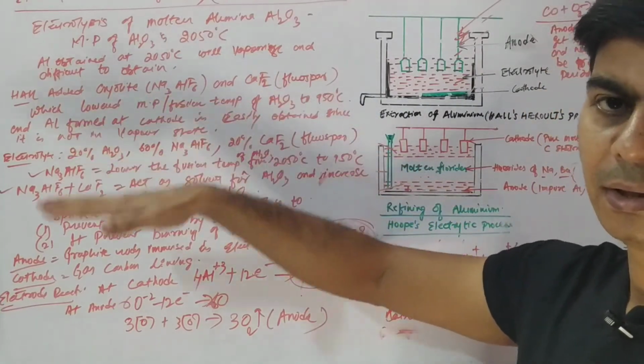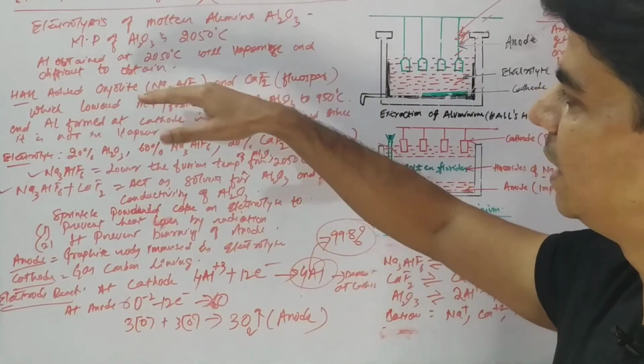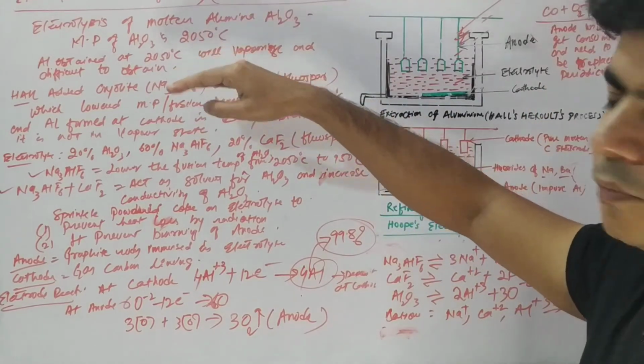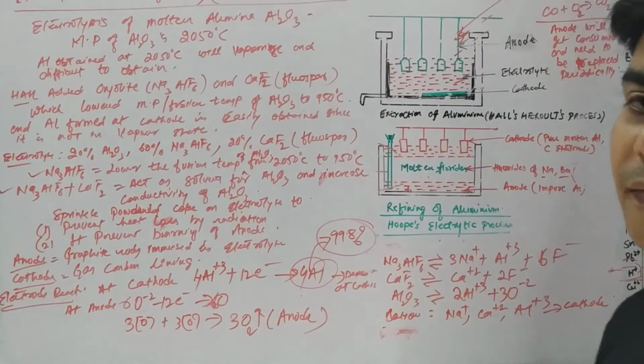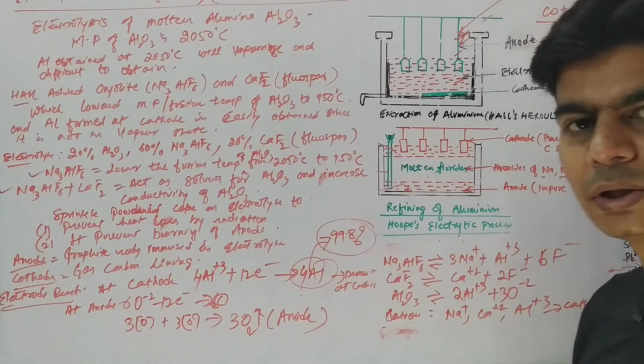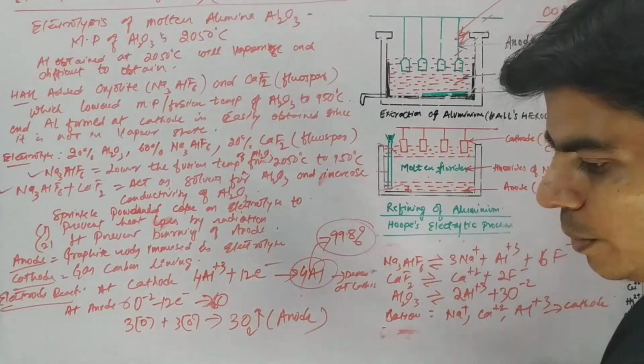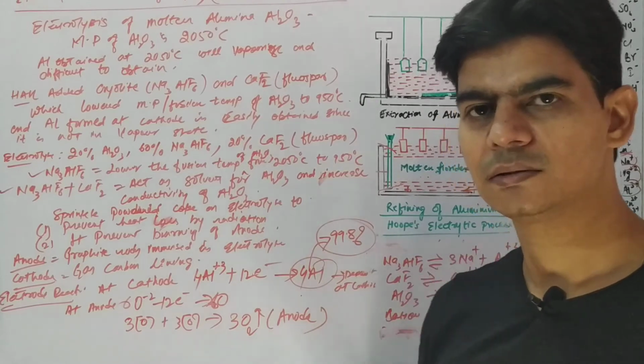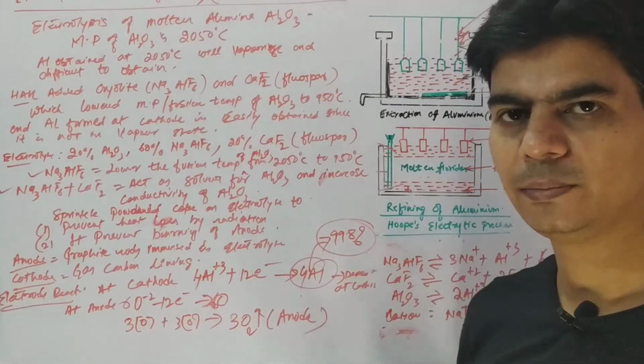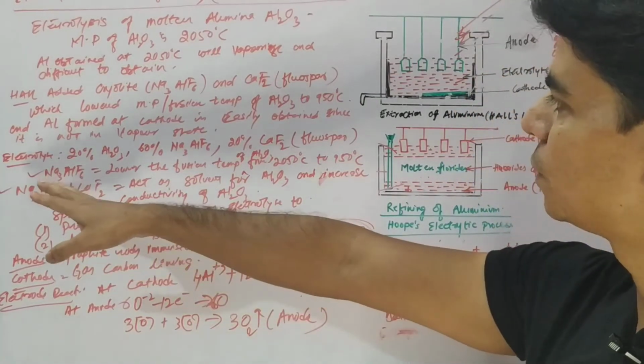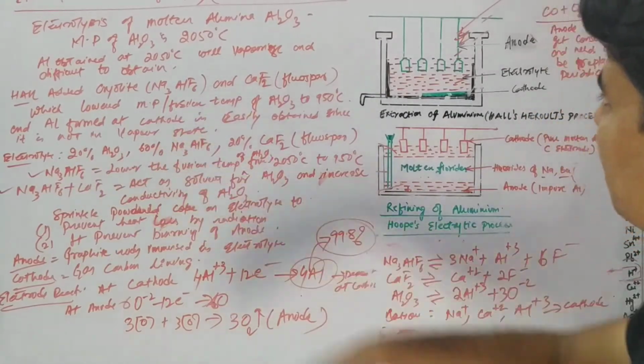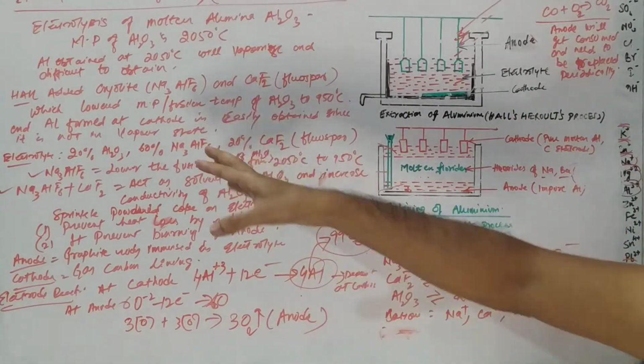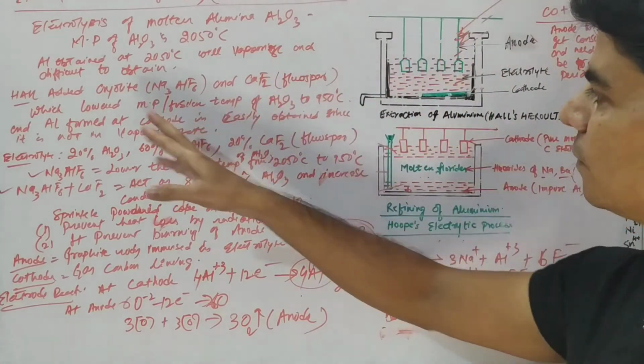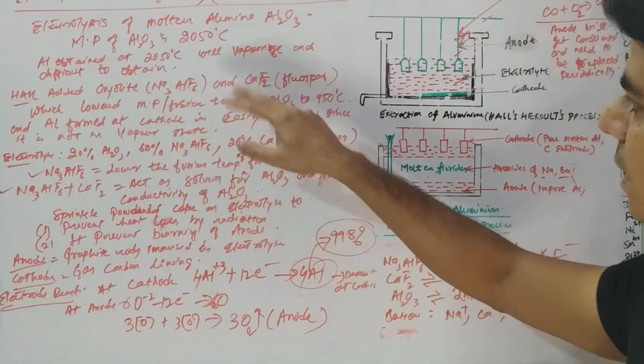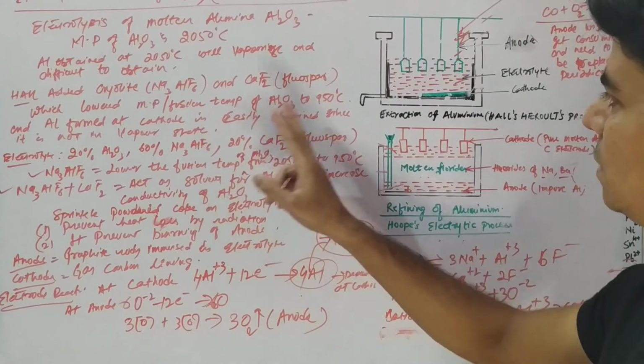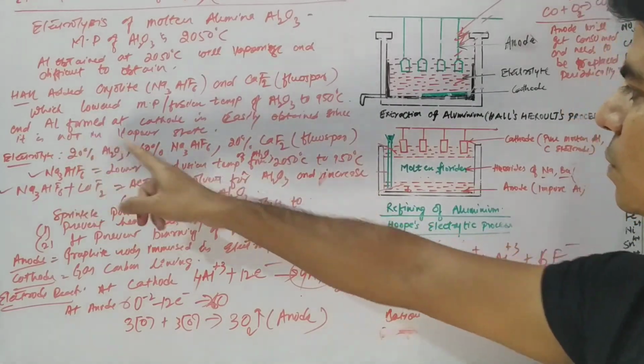So what cryolite did, it lowered the fusion temperature or melting point of alumina from 2050 degrees Celsius to 950 degrees Celsius, right? Due to which the aluminium which is obtained at 950 degrees Celsius is not in vapor state, so it could easily be obtained, right? And when electrolytic reduction of alumina was done with this cryolite and calcium fluoride, it is easily obtained, as it is not in vapor state.